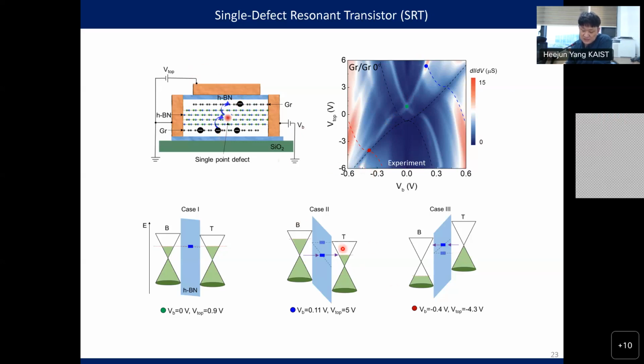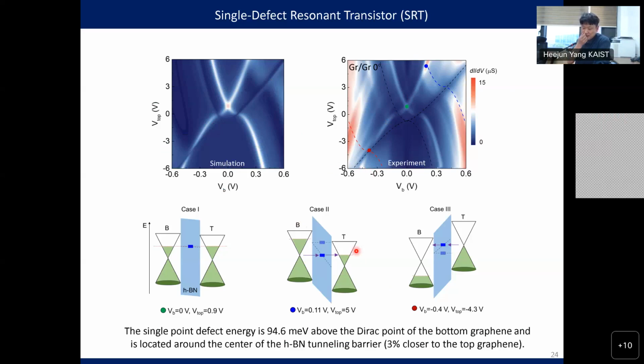Anyway, this is resonant tunneling, and similar data have been reported as well. But you see the left mapping, the simulation. This is what we simulated. So this is very simple. We just use MATLAB, Mathematica, a very simple coupled equation. So we can simulate just considering the energy difference between the two. And then they look quite similar, surprisingly.